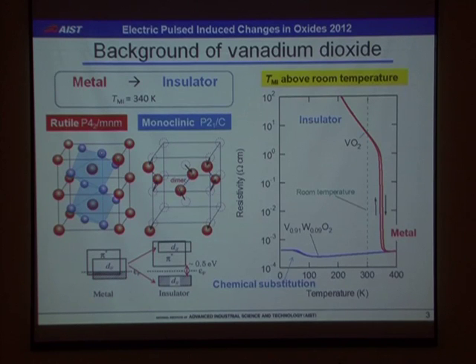So let me start from the background of vanadium dioxide. It shows an insulator-metal transition accompanied with a structure change from the high-temperature rutile to the low-temperature monoclinic phase. Vanadium dimerization occurs in the latter form, which opens a gap at the Fermi level. The most spectacular feature of this material is that the transition temperature is above room temperature. In the resistivity curve, it shows a sharp jump at the transition temperature in the non-doped case. It is possible to stabilize a metallic state by chemical substitution. I will mention this later, but it is possible to stabilize insulating and metallic phases even at room temperature.